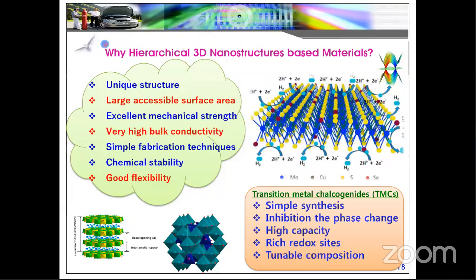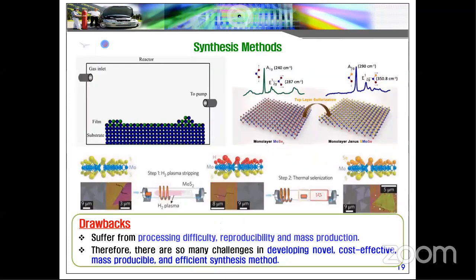So why do we need to develop 3D nanostructure based materials? What are the advantages compared to other nanostructure materials? The 3D nanostructure material has a unique structure. The fabrication methodology is very simple compared to other technologies, and it is chemically and electrochemically more stable. That material has good flexibility, especially the transition metal chalcogenides. We can say metal sulfide and metal selenide based materials. People used metal sulfides previously. Nowadays, people are moving to selenides due to more active sites, and selenides have higher porosity compared to sulfides. So in order to increase the porosity, we are going for metal selenide based materials and synthesis methods.